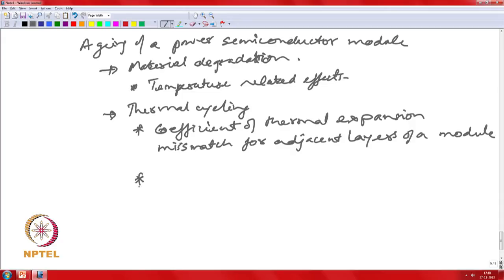Another factor to keep in mind is that even if you have closely related thermal coefficients of expansion, your temperature is not uniform. Adjacent layers might be sitting at different temperatures. Your junction temperature might be 125, and your case temperature might be 70 degrees. So the actual temperature is different across the different layers.